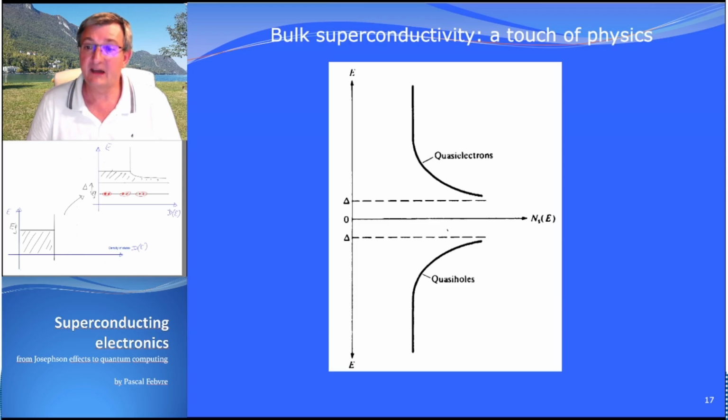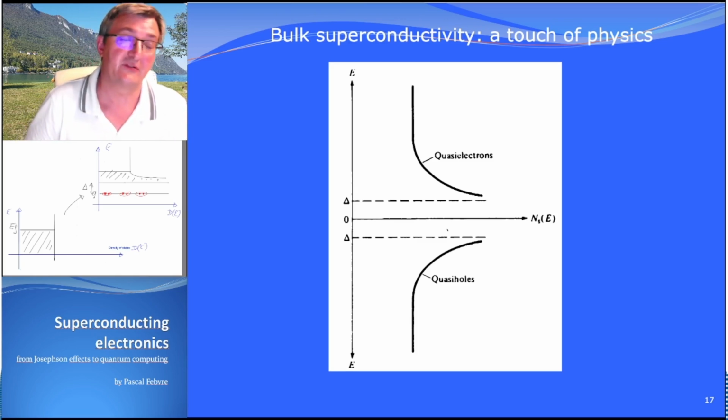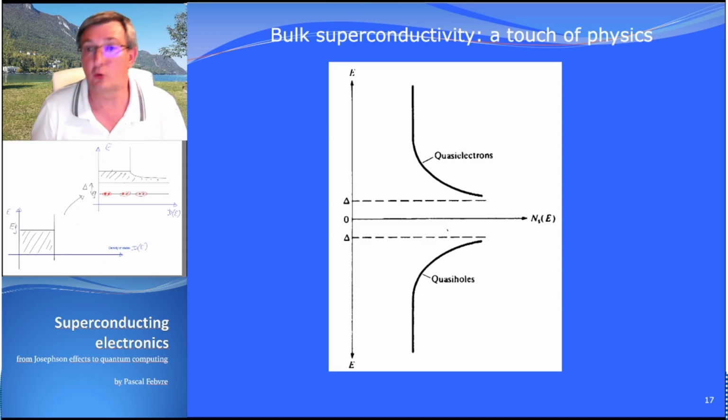So this gap is, as I told you, an important feature of superconductors, of the order of 1 terahertz. And of course, you can understand, especially with the phase transition theory, that this gap corresponds to the order of the system. If you are at high temperature, the metal is normal, there is no gap, and there is no order. These electrons have collisions between themselves, and so you can consider the order parameter is 0 in phase transition.